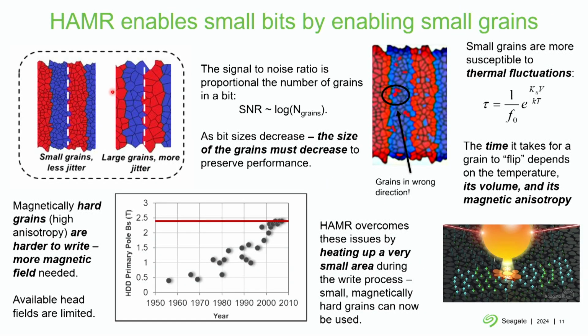The main problem, like I said, is I need to decrease the bit size, which means that I need to decrease the grain size. If I don't decrease the grain size, and I have fewer grains per bit, and the grains are big relative to the bit size, the transition in between two different bit polarities is not going to be very straight. And this is a significant source of noise. So the media SNR is proportional to the number of grains in a bit. So our goal is to try as much as possible to maintain the number of grains per bit, even though that's actually quite difficult.